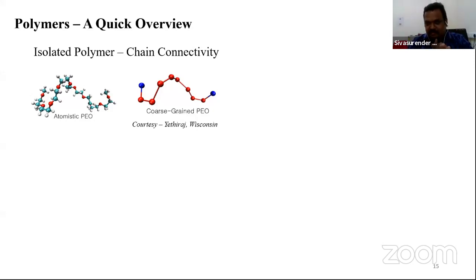And at this level of the polymer, there are so many local degrees of freedom which dominate the behavior of polymers. So for simplicity, let me discuss with you today only polymers which are electrically neutral, and the interactions between all the neighboring monomers are screened within the size of a monomer, which essentially means that energetic interactions are completely removed. And these are not just a theoretical construct. There are polymers which can actually realize such a situation, be it polystyrene or polymethyl methacrylate, in proper ideal solvent conditions, they don't exhibit any interactions, right?